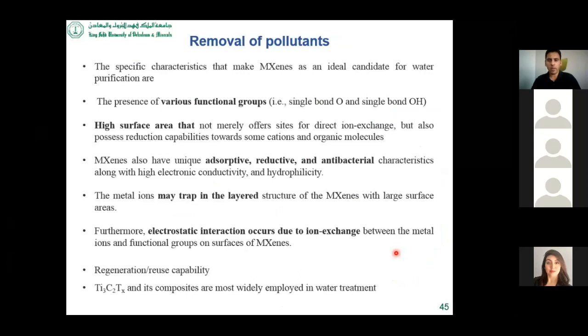So if we talk about the removal of pollutants, why will it remove pollutants from water? Because it contains various functional groups, and again, you can modify the surface to introduce some more groups for your desired applications. It has high surface area, which is specifically required for adsorption. So this means that there are more sites where the molecule can be adsorbed on the surface. It has adsorptive property, reductive property. It can reduce the molecule from one state to another. For example, it can reduce chromium 6 to chromium 3.